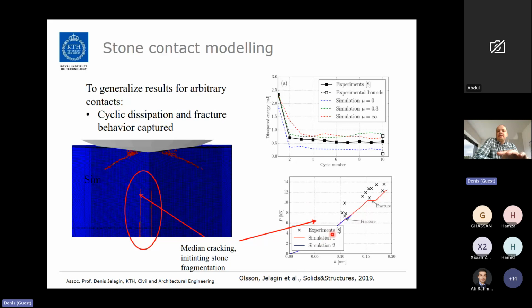The blue and red lines here are the simulated force displacement response. As you can see, we can capture those jumps in force displacement curves quite well. And those jumps correspond to the formation of median cracks in the material. So here we have the stone to indenter contact area. The red stuff on top are Hertzian cracks, so ring cracks on the surface, and then they propagate into a cone. And those big cracks form unstably, and those are the cracks corresponding to those jumps in force displacement curves. The crosses are experimental data from an experimental study.